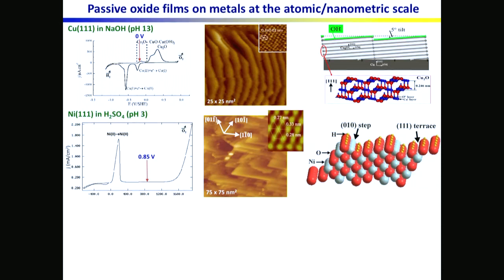What you can see also is that some of the steps are aligned and show perpendicular shapes, and some others do not. And as I will not go back to that later, I would like to point out that this is a very interesting feature, because from this kind of image, we can look as a function of time to the slow dissolution that is still taking place in this range. And we can show how these steps evolve as a function of time at the applied potential. And if we do that, we found that steps that are rough are dissolving much faster than the steps that are aligned like this one. So this one would remain stable for a very long time, whereas the steps that are rounded would dissolve.